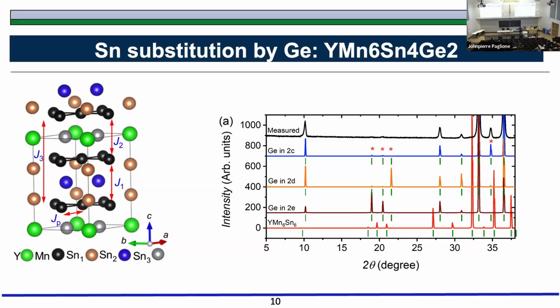The beauty of this structure lies here, because you see here, between these 2 layers, you have only tin atoms. These 2 different colors are tin atoms, right? Although they are sitting in different crystal sites. But between this and this layer, if you look at here, you have this rare earth element, Y, which is yttrium in this case, as well as tin atom. So the interaction through this layer and the interaction through this layer can be different.